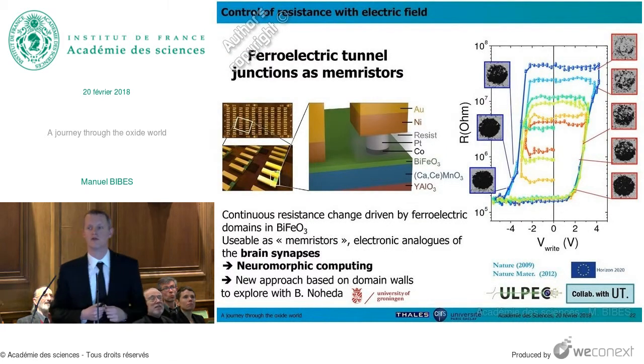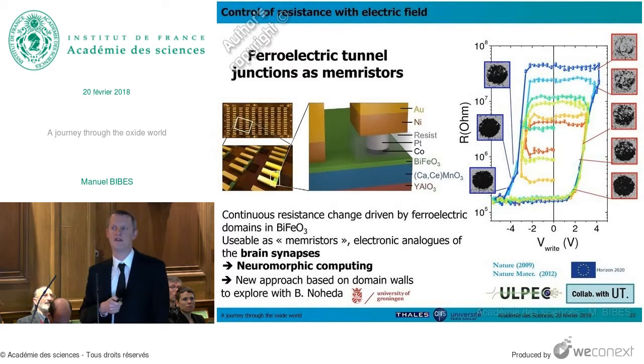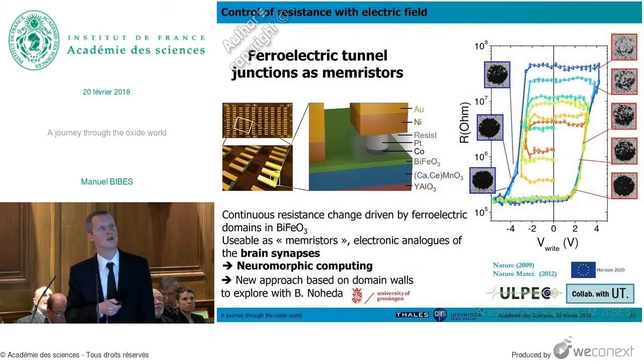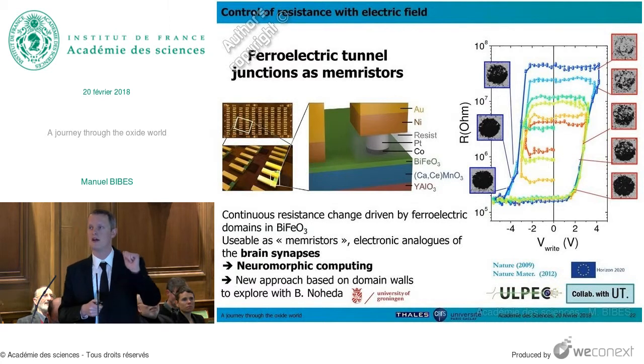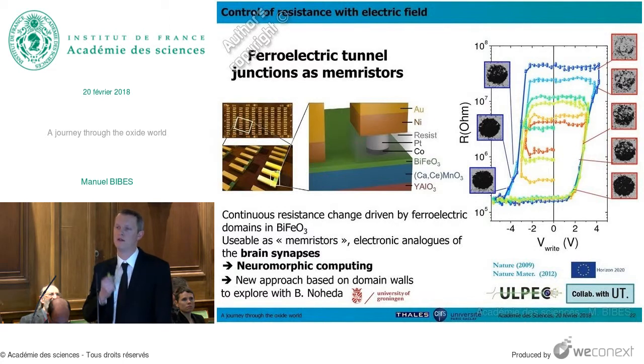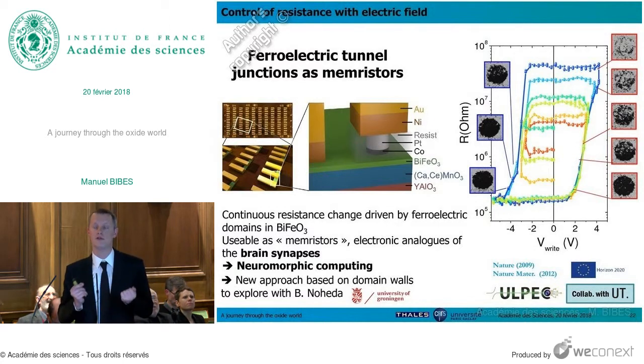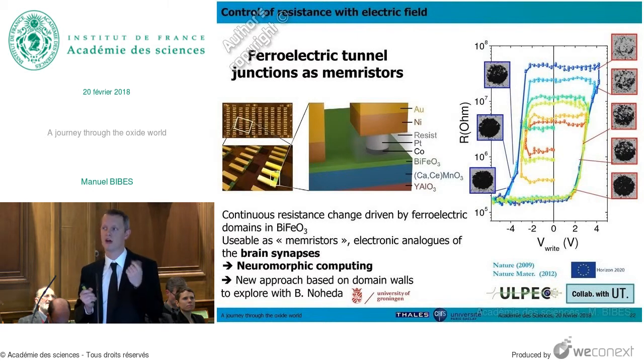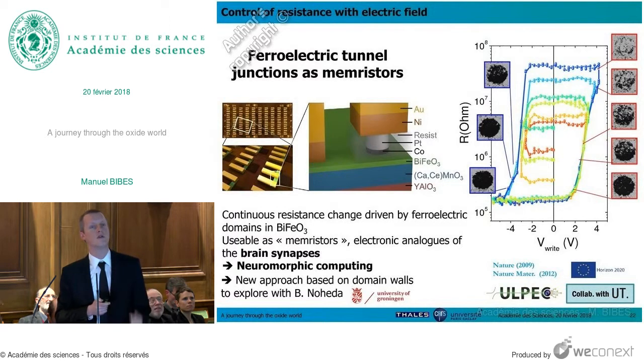Another example that I want to show you, it was mentioned briefly in the introduction. It's these devices which we call ferroelectric tunnel junctions. So we have, again, the same material that I showed before, bismuth iron oxide. Very thin layers, just a few atomic layers. And here what we are going to do, we are going to apply a current perpendicular to the layer. And the resistance of the material, as we discovered, is extremely sensitive on the direction of the electric dipoles of the ferroelectric bismuth iron oxide. So when the polarization is pointing up, we have a very low resistance. When it's pointing down, we have a very high resistance.